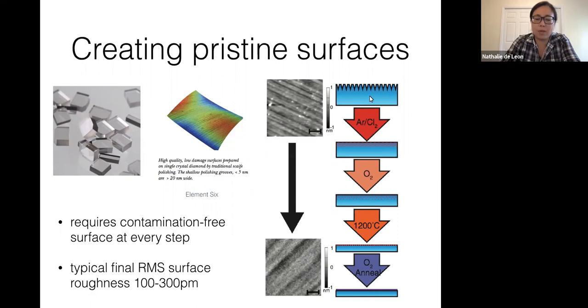So without going into too much detail, what this process generally looks like is we start with very high quality polishing. We can do reactive ion etching to remove the subsurface damage from polishing. That leaves behind some RIE damage, like implanted chlorine ions. So then we have to do some further RIE to remove that damaged layer, some thermal annealing to intentionally graphitize the top few nanometers of material. And then finally, we can do a chemical anneal to actually fix the chemical termination of the surface.